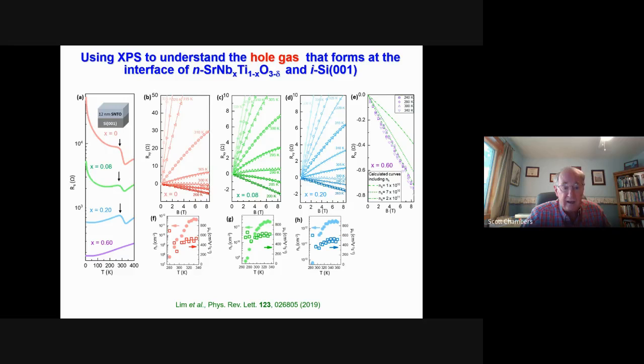If you then analyze the Hall data to extract the electron mobility, you find that the electron mobility is up around 500 or 600 centimeters squared per volt second. That can't possibly be in the STO because the mobility is probably 1,000 times too high or more, because hole mobility in STO is extremely low. So this indicates that there is a hole gas forming in the silicon. So what in the heck is going on?